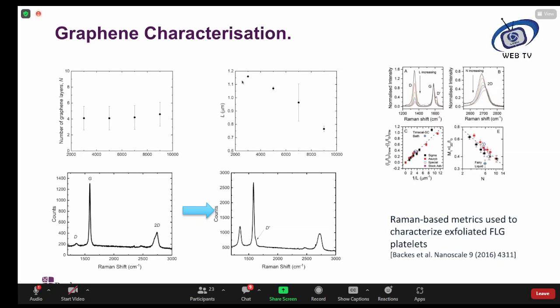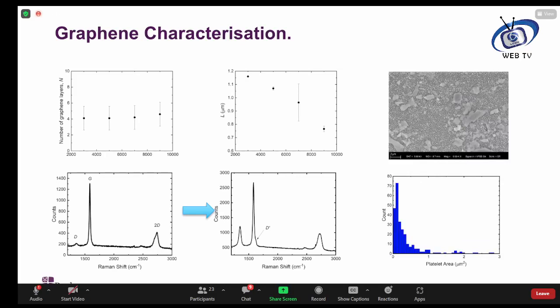However, if we increase the shear speed during shear exfoliation, we make the platelets smaller. They vary in linear dimension from just above a micron to about 0.75 micrometers. We also check the linear dimensions by using scanning electron microscopy. And here are a bunch of graphene platelets that have been filtered onto an anodic aluminum membrane, and we simply count them, and we count their areas.